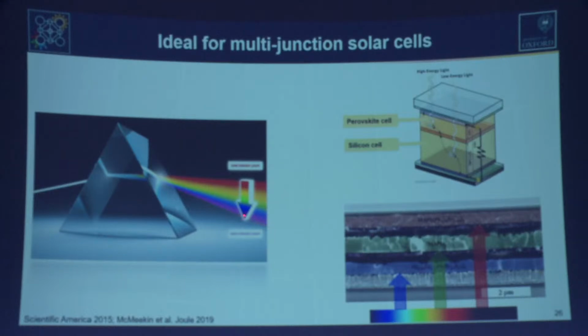But if you stack solar cells on top of each other, you can get more of this electron volts of energy converted to electrical energy, so you can get higher voltage from the cells. For instance, if we put perovskite on top of silicon itself, we can fundamentally increase the efficiency. The absolute limit of efficiency for silicon is about 29% efficiency. We could pump that up to 45% at the thermodynamic limit, the limit of what that could ever do.